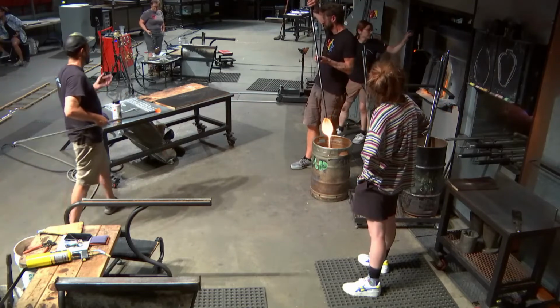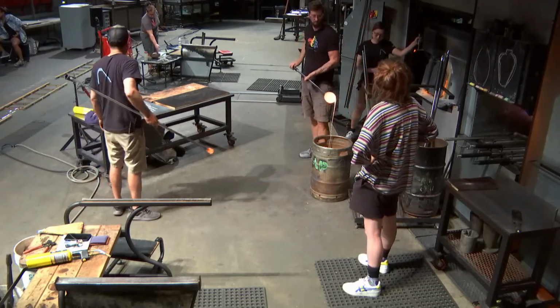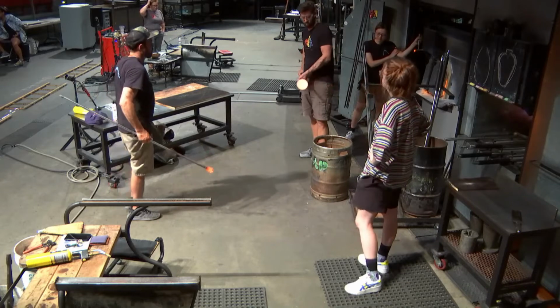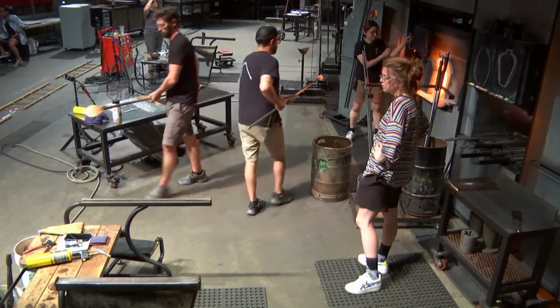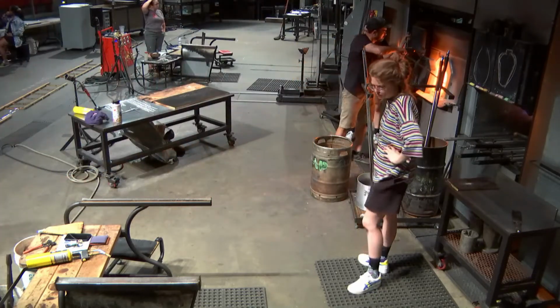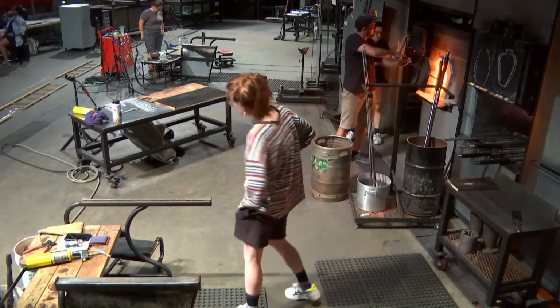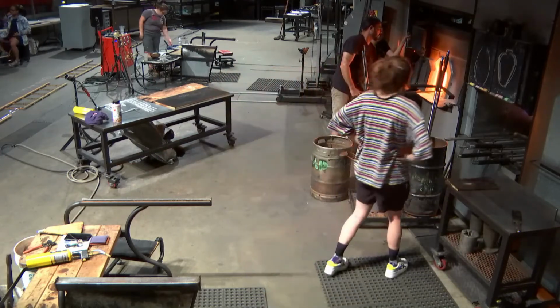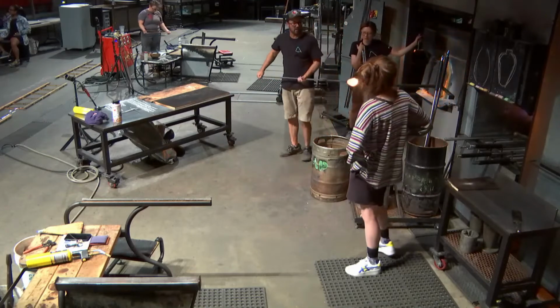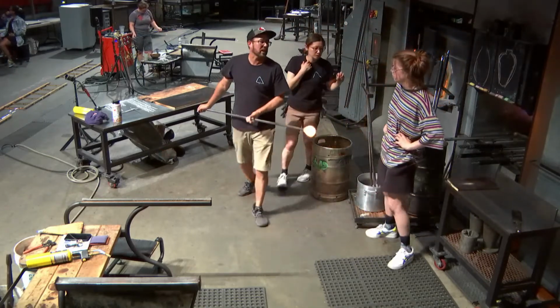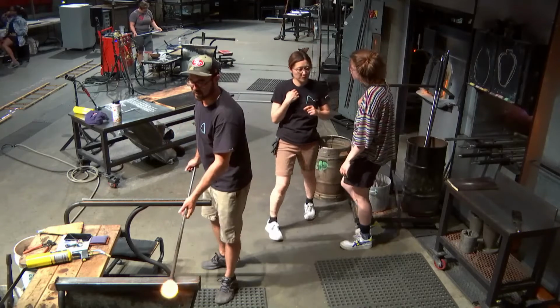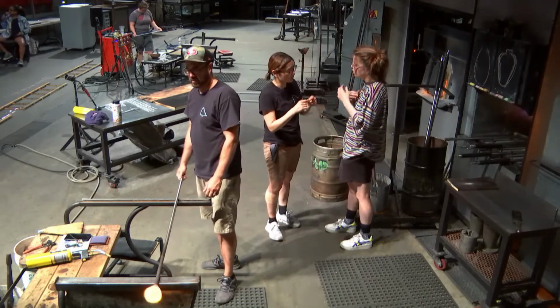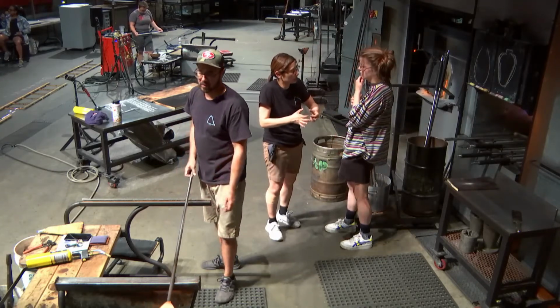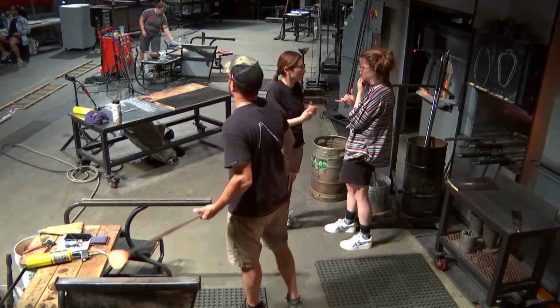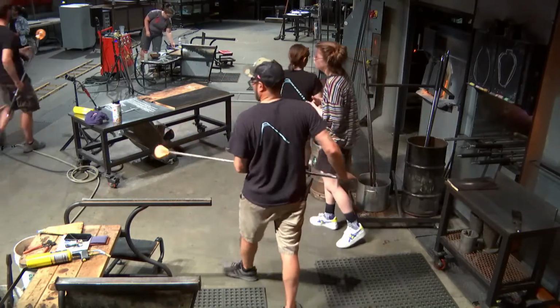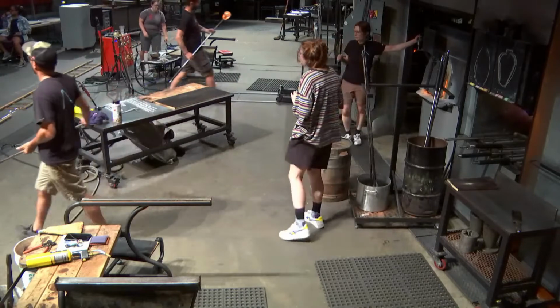We'll strip some of that extra glass off, and all of the glass that is stripped into that bucket will be reused because it has not been cross-contaminated with color. Today we're not using any color in our process, which is really cool because often we put a lot of color on glass. Color is applied to glass in many different ways here at the Hot Shop. It's chopped glass, which is frit, pulverized glass, which is powder, and color overlay, which is preheated color bars laid over a clear bubble.